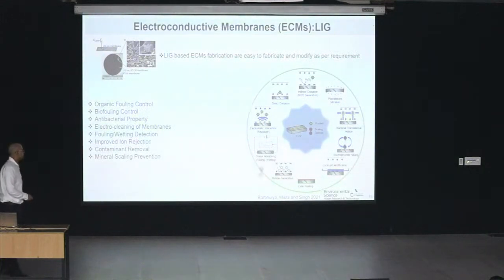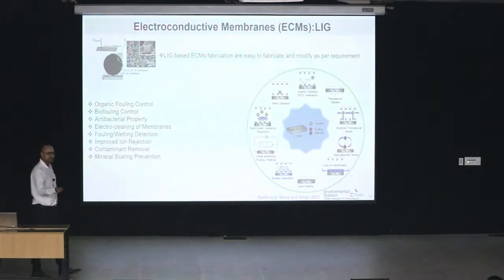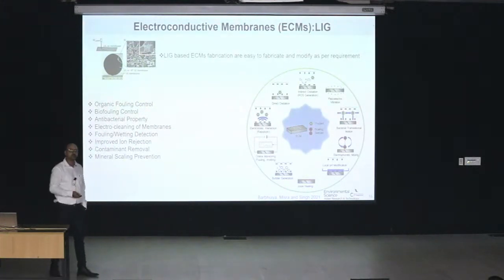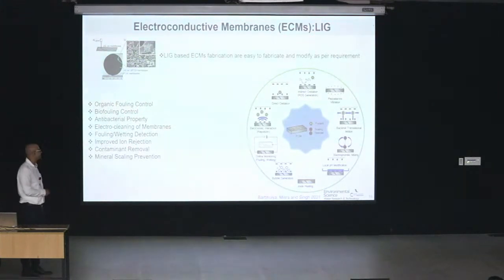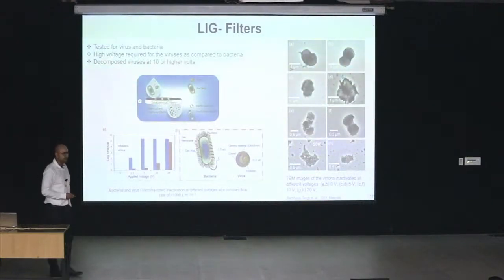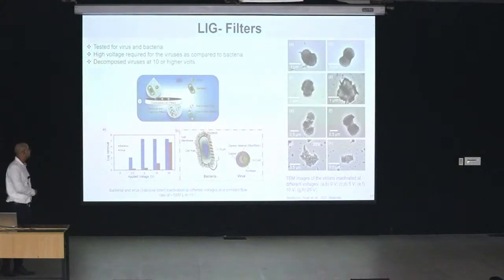So here you can see we have recently published a very good review article where we have demonstrated what different kinds of electrical properties we can harness, and then we can solve different problems in membrane technology. It's starting from fouling to disinfection, and also we can degrade different kinds of newly emerging contaminants like pharmaceuticals, and also we can sense fouling because these surfaces are conductive. So just by the change in the electrical property, we can easily sense how much fouling is happening on the membranes. So with this, we have demonstrated several things in the last 4 to 5 years. For example, recently we have demonstrated how these filters can kill different kinds of viruses, especially during COVID time.